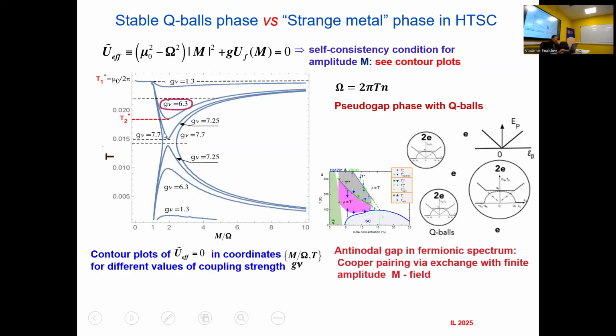And when G nu grows, finally you get a special G nu value when the upper branch touches the lower branch. And then you see this is indeed optimal doping because then T star becomes equal to Tc. And now, of course, it is interesting to find out how these parameters mu sub 0, G and nu define these temperatures T star and Tc. Well, of course, when we are above, then you see that you have T star 0 and T star 1 of this strange metal region. For example, if you start on this branch, here the first solution appears and here it disappears. So you have strange metal region in temperatures T1, T2.